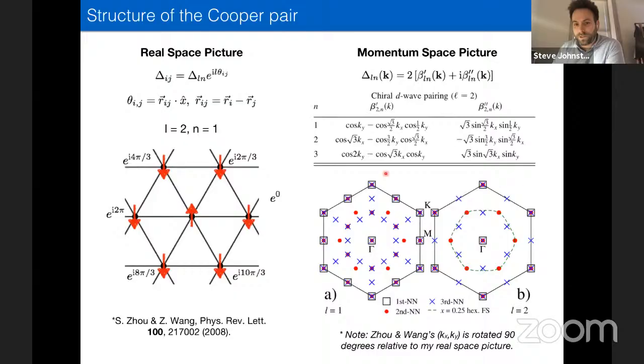And so in a lot of these cases, what happens is the d+id actually doesn't have a node sitting on the Fermi surface, which also helps explain why we had trouble distinguishing it from an S-wave case, because we don't have a node that appears in the Fermi surface. And so you don't expect the same sort of V in the density of states that you would get for D-wave superconductivity in, like, the cuprates, for example.